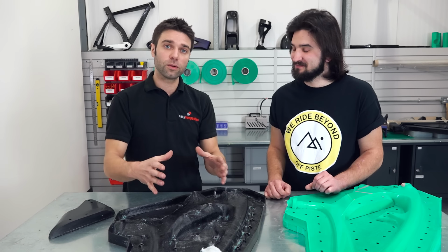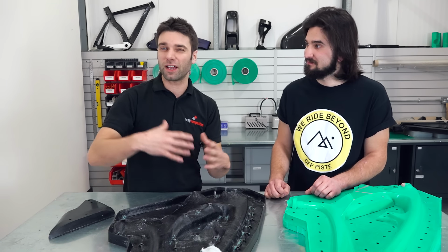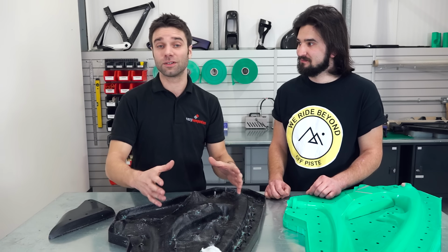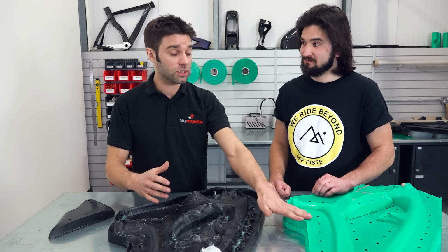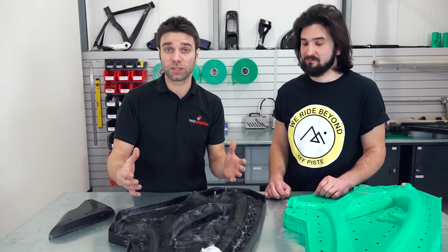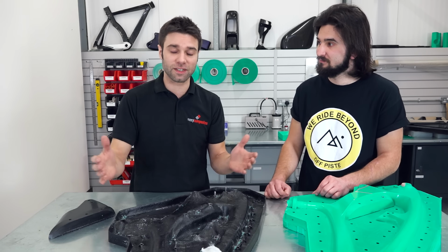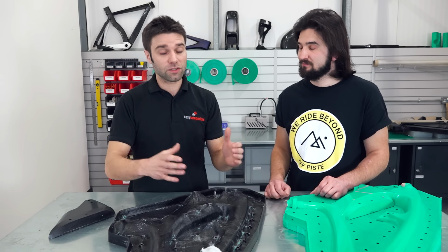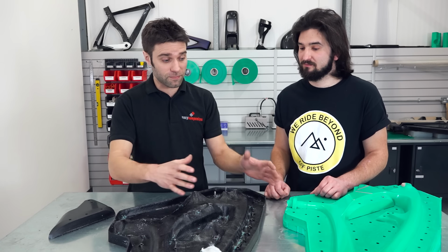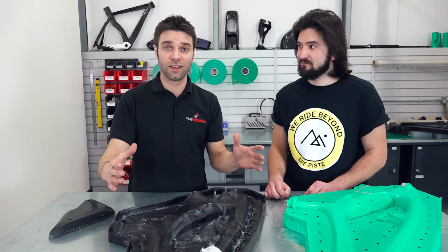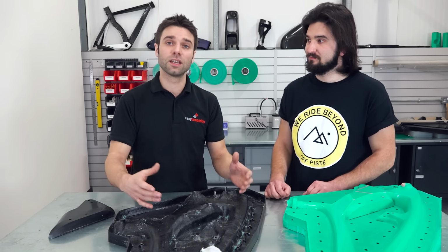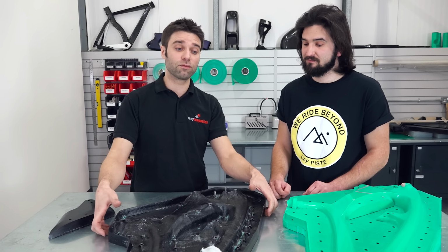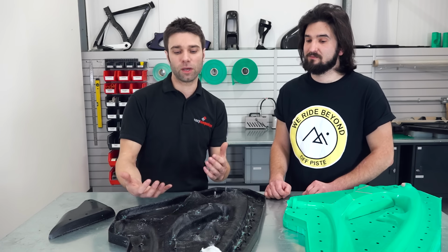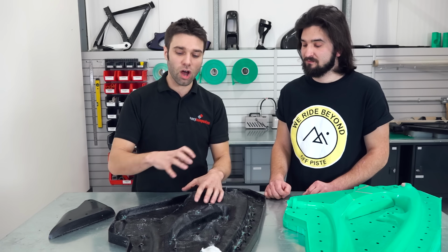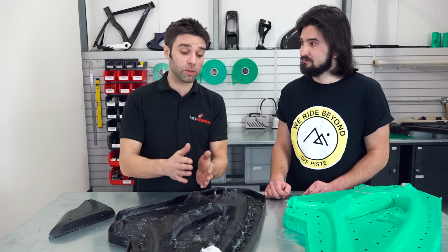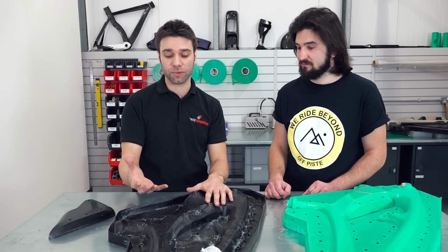So the reason for a low temperature cure, why not just take it right up to say 120 degrees and do the cure at that temperature, is that epoxy model board actually expands. All model boards do, and all materials expand at different rates. And if we went straight up to 120 degrees, this pattern would actually be larger than it was originally machined. So it's cured at a low temperature, it's then removed from the pattern and then post-cured, and that does the final hardening of the mould and makes it able to operate at its final service temperature.